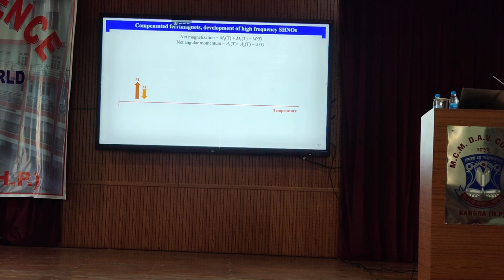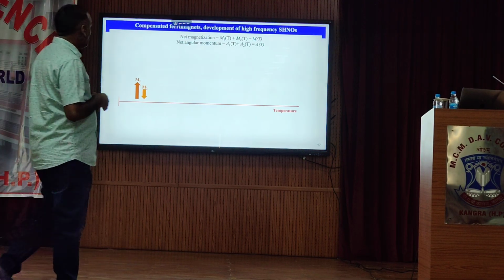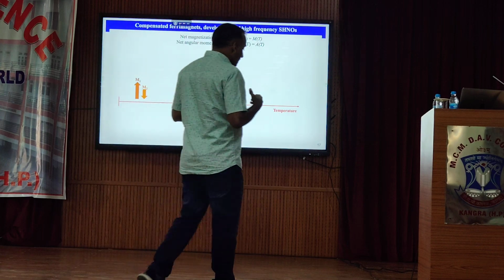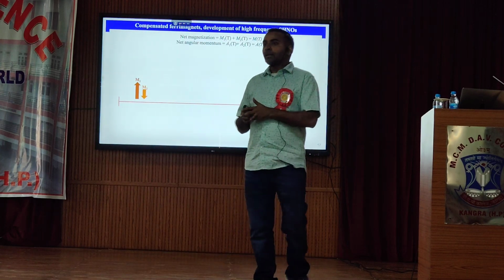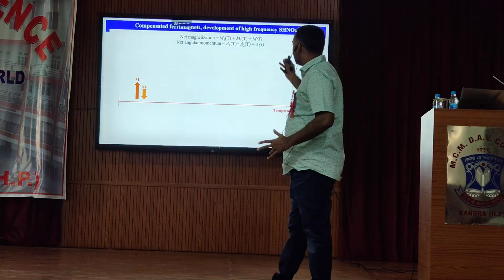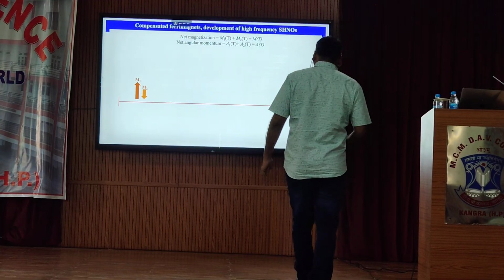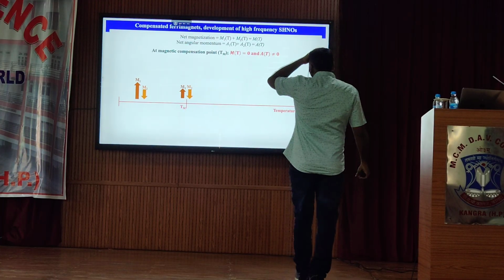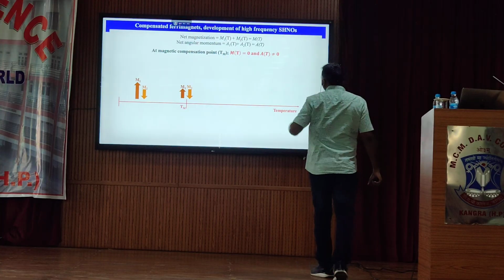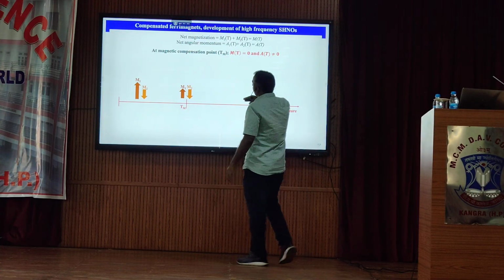If you are working on a device based on antiferromagnets and the magnetization is 0, it is very difficult to detect that signal. The signal is almost 0, so we cannot detect it. To detect the signal while sustaining dynamics close to antiferromagnets, these materials are a very prospective candidate. As we change the temperature in these types of materials, the sublattice magnetization changes.